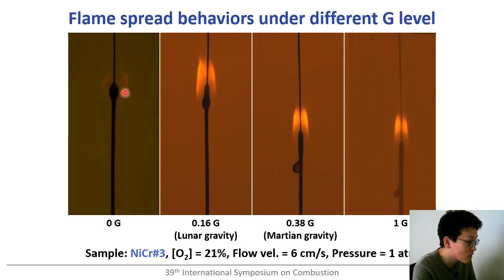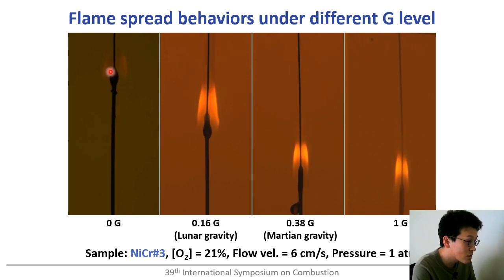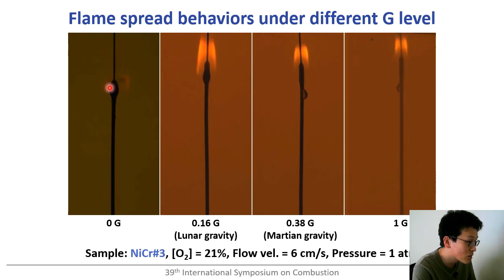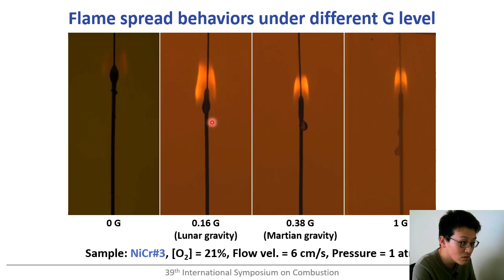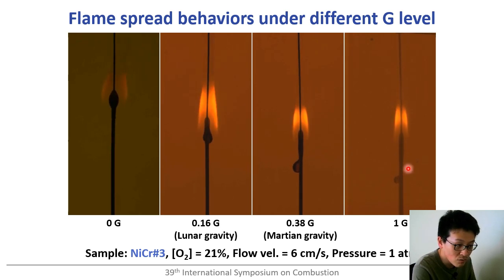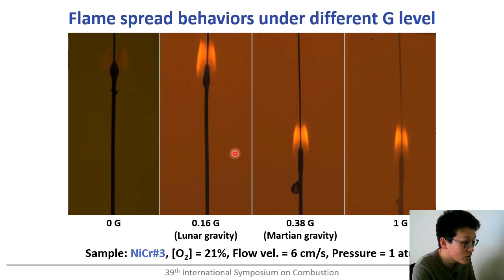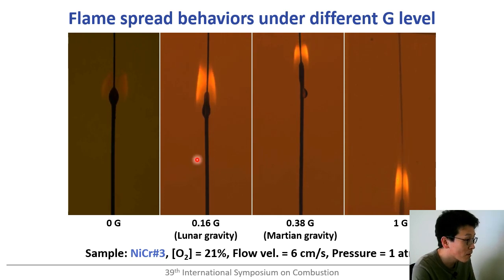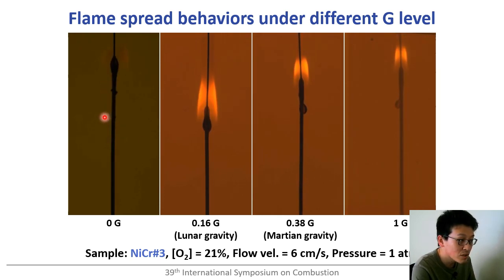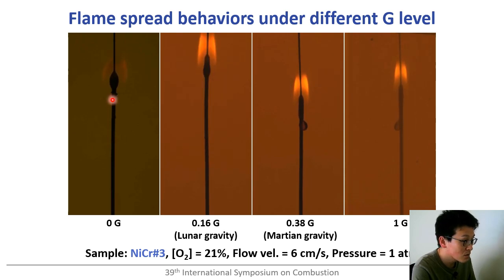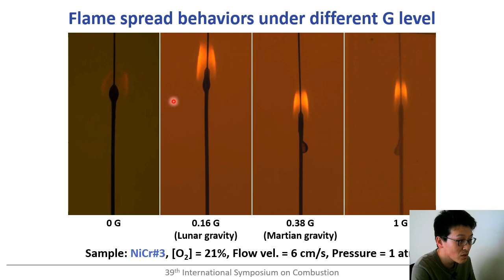For instance, in the normal gravity and zero G conditions, molten polymer is accumulated in the flame, and it forms an ellipsoidal shape due to surface tension. However, as the gravity level increases, it is stretched in the downward direction and eventually drips down along the wire surface. This is one of the unique behaviors observed in the partial gravity experiment. Additionally, the flame shape is also affected by the gravity level. As you can see, as the gravity level increases, the diameter of the flame becomes smaller due to the enhancement of natural convection.